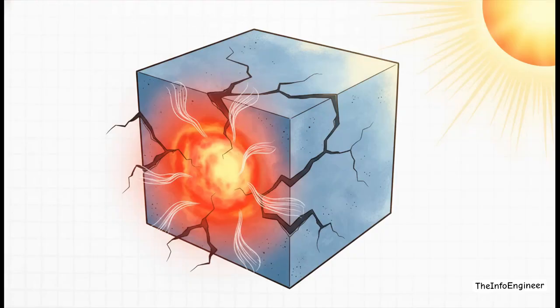So what actually happens to this delicate balance of skeleton and muscle when you're pouring in extreme heat, like what we constantly deal with in Pakistan? Well, when ambient temperatures soar, that exothermic hydration reaction, the chemical process that naturally generates its own heat, goes into overdrive. Temperatures inside the core of the concrete can easily spike to 160 degrees Fahrenheit.